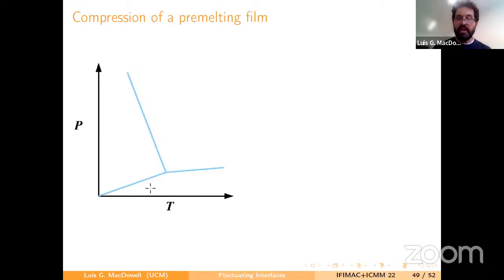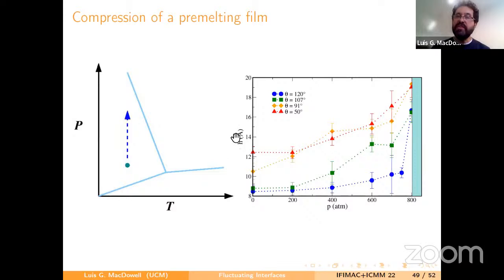So consider that we are initially at 1 atmospheric pressure. And because of the asperities, the film here at this pressure increases its pressure. It's being pressurized, okay? It's compressed. So you increase the pressure, what is happening? You are approaching the melting line. So this means that the free energy cost of making a pre-melting film, which is liquid water essentially, is actually smaller.